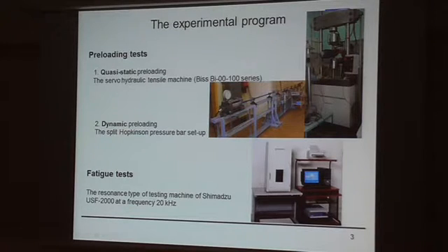Dynamic preloading of samples was achieved in the split Hopkinson pressure bar setup, and quasi-static preloading was carried out on a servo-hydraulic tensile machine. And fatigue tests were carried out on a resonance type fatigue testing machine at a frequency of 20 kHz.